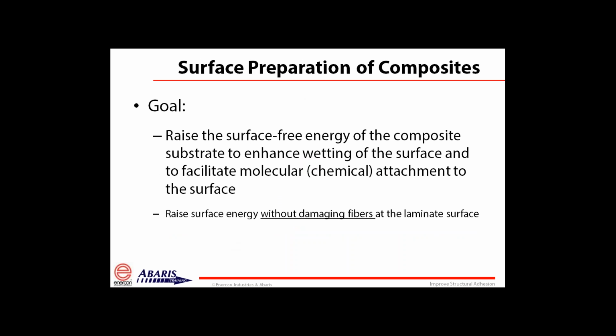So the goal for surface preparation of composite materials is to do this. It is to change the chemistry on the surface of the composite to raise the surface free energy of that composite substrate, to change the polar groups on the surface of that composite substrate so that it allows for proper wetting of the surface and proper bonding with the adhesive that has been selected for that application.